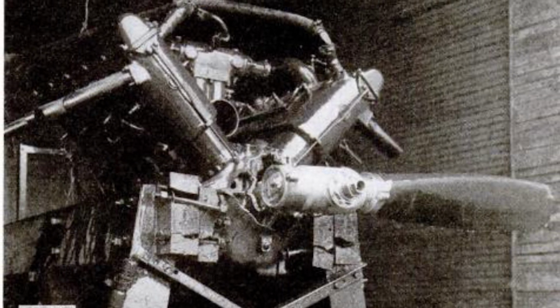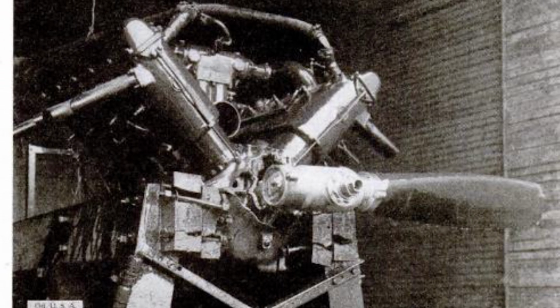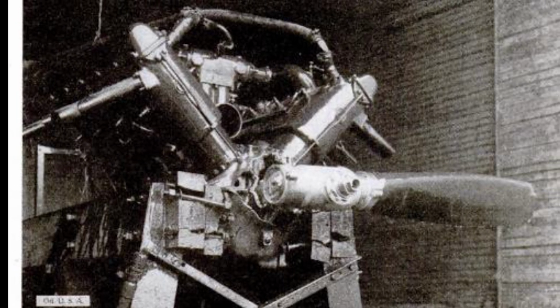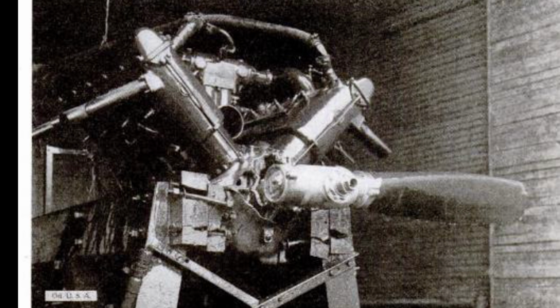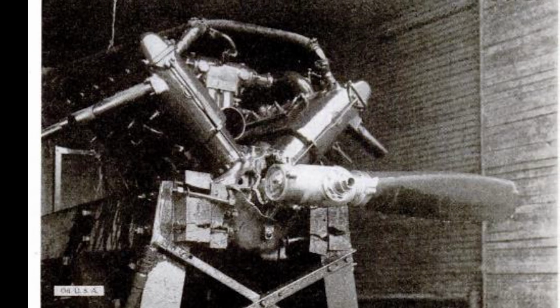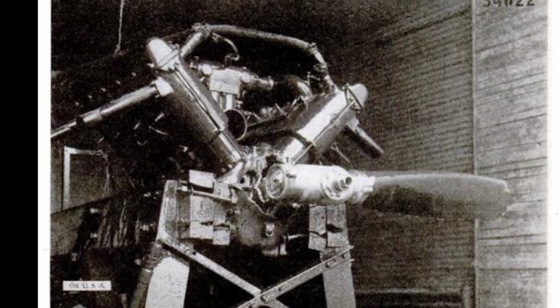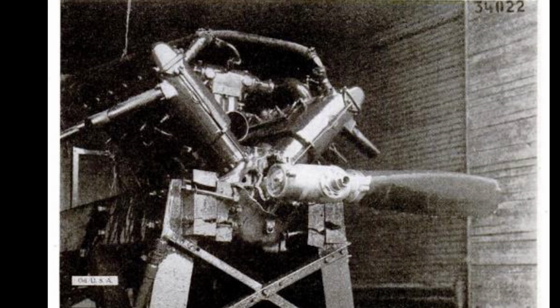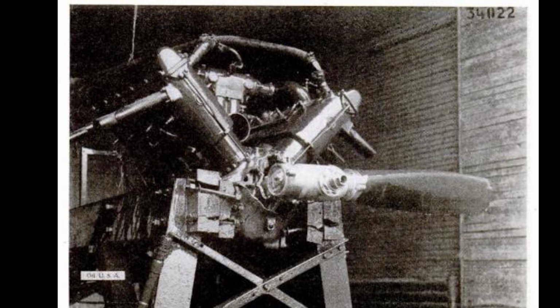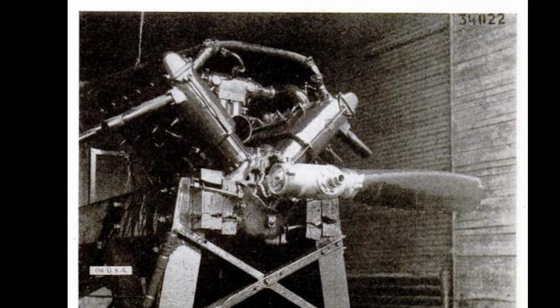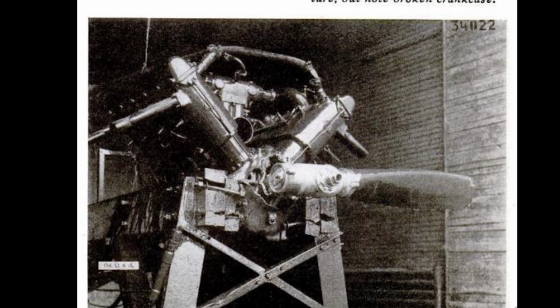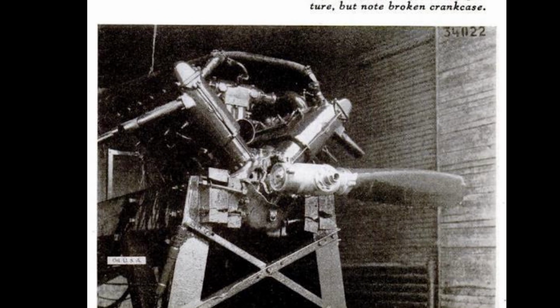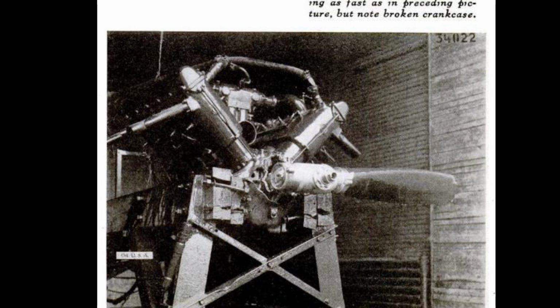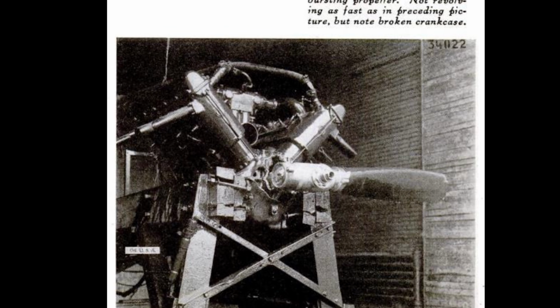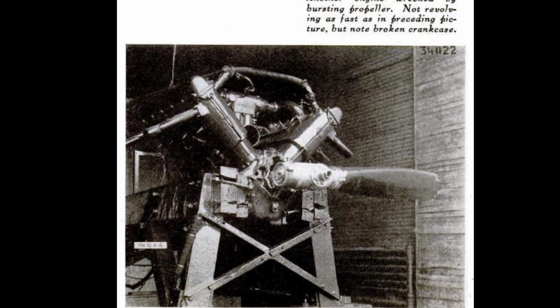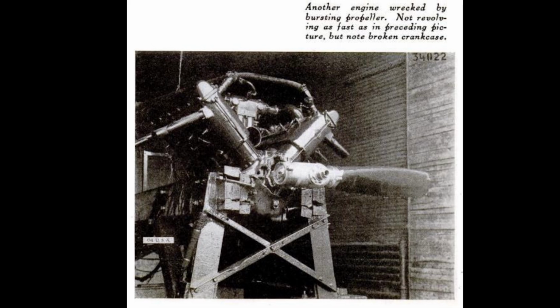If one blade breaks off entirely, the 20-ton whirling pull of the other blade instantly shatters to pieces the light but sturdy engine to which it is attached. The break of a blade may be due to flaws in the metal, since in forging the blades invisible seams are sometimes formed which extend through the propeller from end to end. These seams cannot be detected except by cutting off a piece of the metal, so the problem has now been solved by forging each propeller with a projecting portion on one end, which is cut off from the rough forging and tested. If any pores are found, the forging is scrapped.